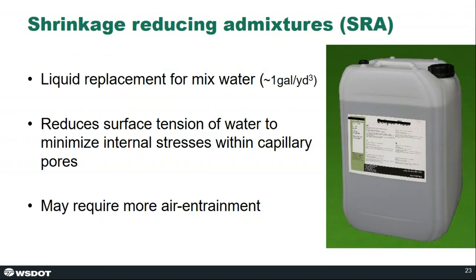So a little bit more about shrinkage and the use of shrinkage reducing admixtures. That shrinkage requirement of 320 microstrain basically requires the concrete supplier to use the shrinkage reducing admixture. It's a liquid admixture. It replaces the mixing water at about a 1-to-1 ratio, and we see about 1 gallon per cubic yard of concrete. And this reduces shrinkage by reducing the surface tension within the water. This minimizes the internal stresses that develop within the capillary pores while the concrete is hydrating, to reduce the amount of shrinkage the bulk concrete experiences.